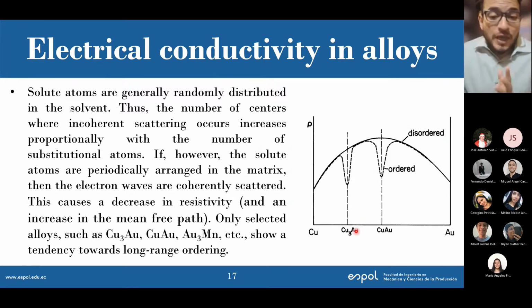And also, that's why if I have a 3-to-1 atomic ratio, right? So 3 parts of copper, 1 part of gold. I have a higher resistivity compared to having pure copper or pure gold, but it's also lower than having a 1-to-1 atomic ratio, right? So it makes sense. Here I obviously have more solute atoms, let's say gold. So I have more solute atoms, higher resistivity. More solute atoms, but less than in a 1-to-1 atomic ratio, higher resistivity. So it makes sense. It's basically aligned with what we learned.